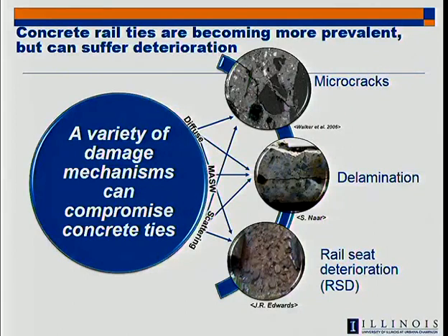So unlike a steel structure, for example, where you may see a fatigue crack, and there's one and you can eventually see it, hopefully, and monitor it, and you say all the deformation energy is going into that one crack, and that's what we have to monitor. In concrete, more often than not, we don't have one crack. We have thousands of cracks distributed throughout the material, which I tried to show here, depending on the deterioration mechanism. But it can't be quantified with one number. Oh, this is a crack, it's so long and so deep.